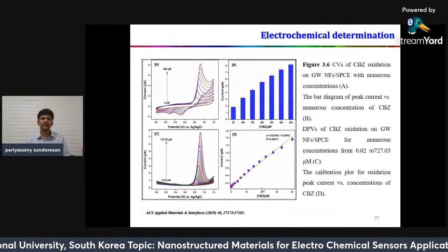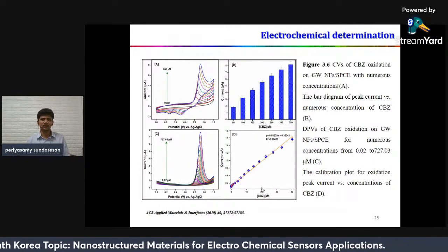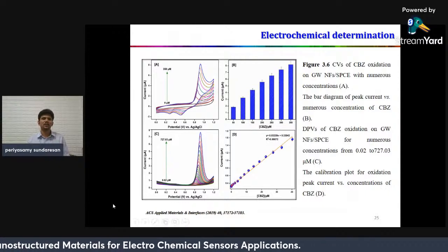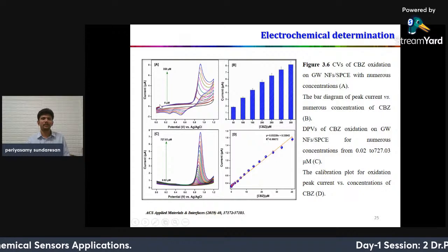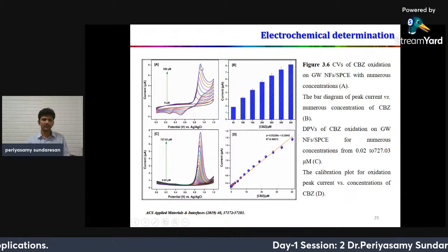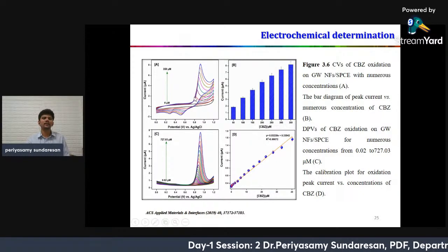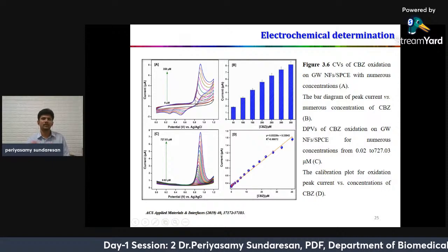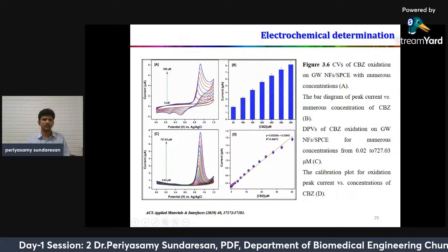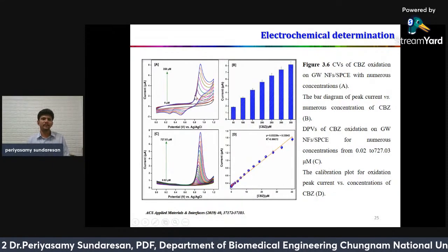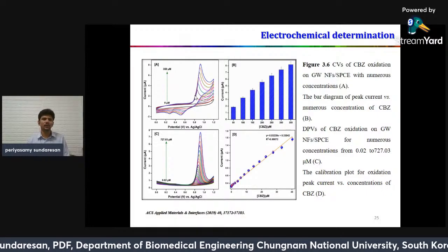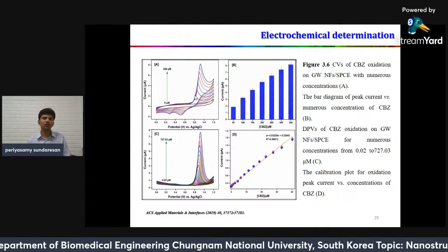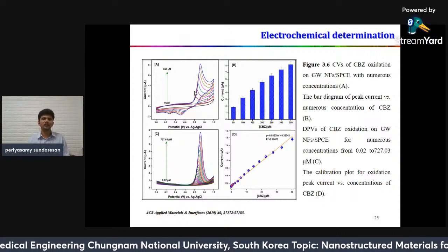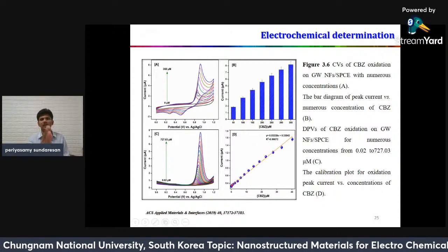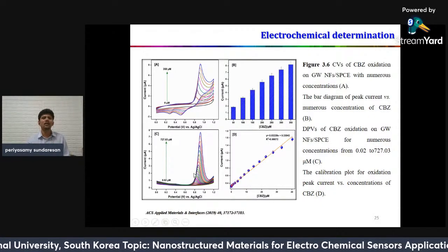The electrochemical determination with different concentrations. The first image is studied with various concentrations of carbendazim. If the concentration increases, the peak current increases, but the peak potential slightly shifts to the positive side, because the pesticide is sparingly soluble in water, and at higher concentration it gives some precipitation. That's why the peak potentials are changing.